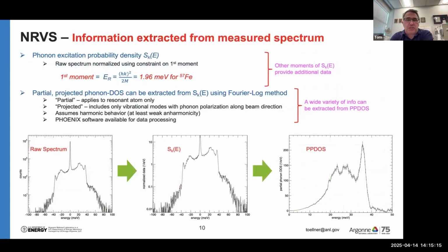So the spectrum, you have the elastic line and the sidebands. These are data shown on a log scale. The plot on the left shows the raw spectrum. This has to be normalized in order to obtain a phonon excitation probability density. And there's a rather robust procedure for doing that, by just making the first moment equal to the recoil energy of an iron 57 atom that's absorbing a 14.4 keV photon. That recoil energy is 2 meV, and so as long as the first moment of the spectrum is equal to that, you then have the phonon excitation probability density.